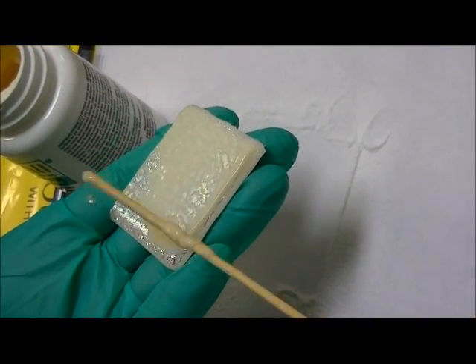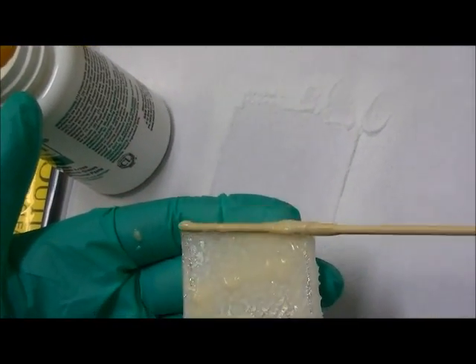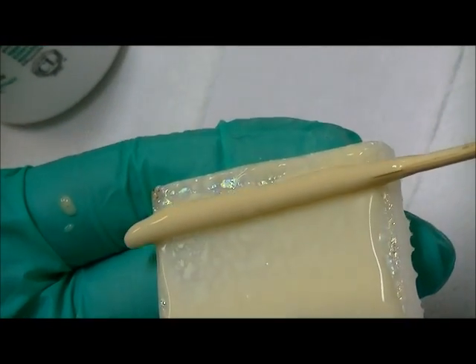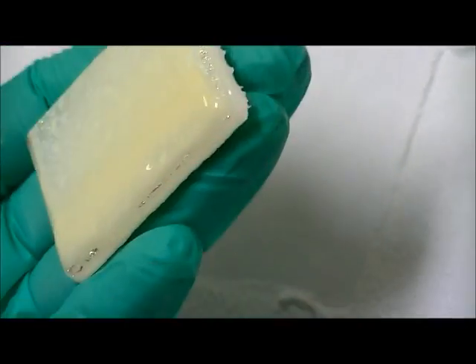I'm using Etch All etching cream. I like it because there's no hydrochloric acid in it. It does take a little longer to etch. If your etching cream is dark brown, which seems to be a question we're getting quite a bit, it's because as the etching cream gets older and older, it turns dark brown, and it's less effective. This is a brand new bottle.